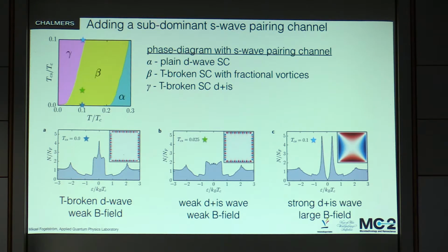And the nice thing with this is, if you would see the net magnetization due to this time reversal symmetry breaking state, there is no magnetization. It's very hard because it's staggered. So the net magnetization is actually 0. So this kind of state, I would claim, could actually have been seen way back, because you could have this splitting happening at a transition temperature and actually showing basically no spontaneous magnetization to be seen in experiments.